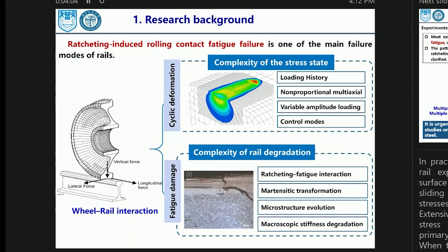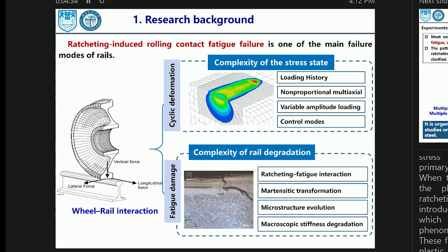In practical wheel and rail rolling contact, the rail experiences cyclic loading, with the surface subject to combined rolling and sliding at relatively high contact stress. Extensive studies have identified cyclic strength and plastic deformation as the primary contributors to rail degradation. When contact-induced stress exceeds the plastic shakedown limit, or the ratcheting threshold, each loading cycle introduces incremental plastic deformation, which accumulates over time. This phenomenon is known as ratcheting.